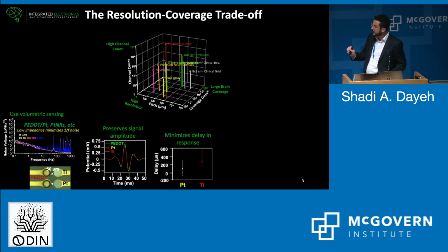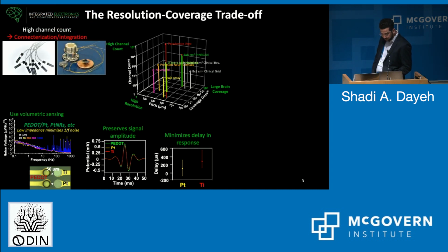This also has implications on the time at which we record the signal, the time delay. Relative to PEDOT, as the impedance increases by 1 and then 2 orders of magnitude, we can have a fraction of a millisecond delay in the recording of the same activity. So as much as we would like to have real-time neural recording, even at the level of the microelectrode, we're really in near real time.